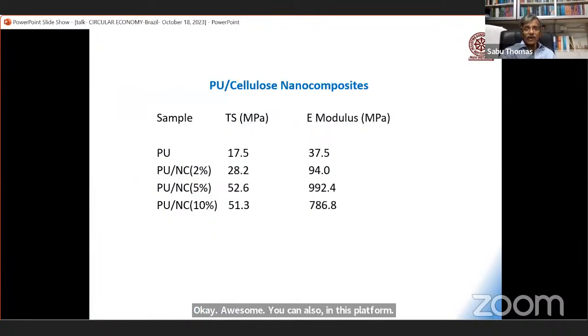Now I'm going to show you some nice work from a university and Sao Paulo University in Brazil. My Brazilian counterpart was very active in synthesizing. Urethane is a very important material for manufacturing. So in cooperation with my Brazilian counterpart, we made a polyurethane cellulose nanocomposite. You can see the neat polyurethane strength is 17.5, E modulus is 37.5. Dear students, you add 5% of nanocellulose made from pineapple fiber, 17.5 megapascal becomes 52.6, and E modulus becomes 990. It's a quantum jump.